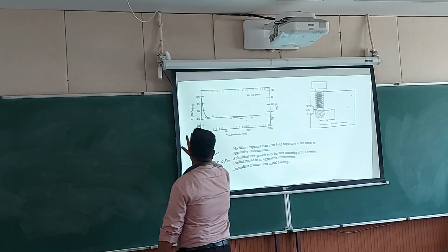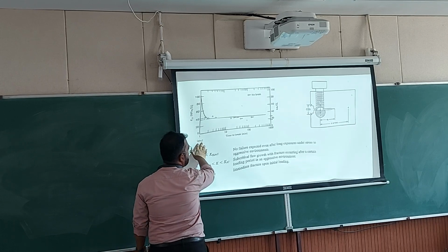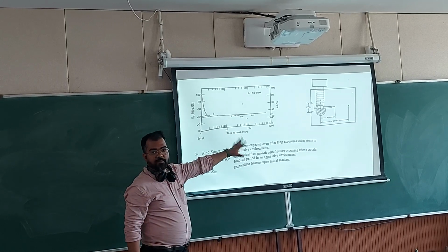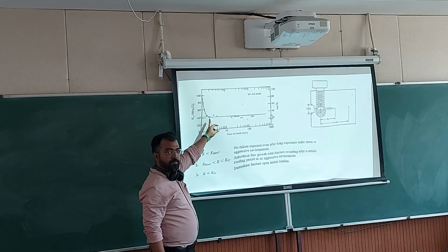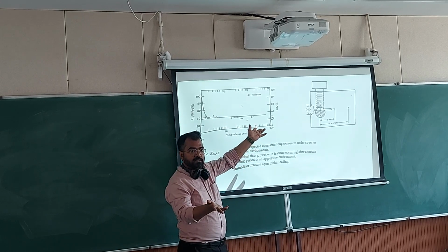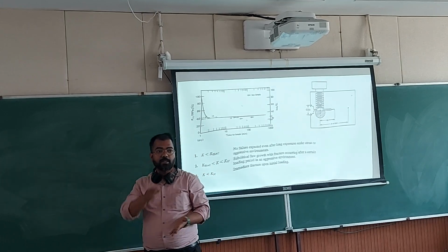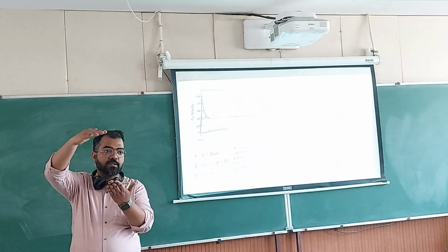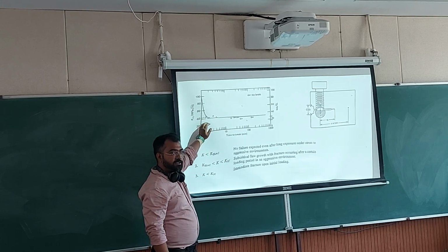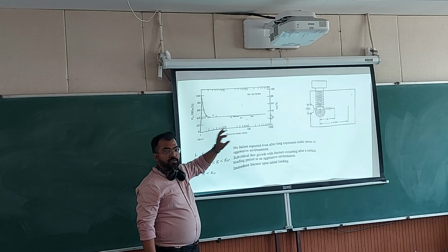And then when you do fracture testing, so you calculate K versus time, and this is dry, so there is no environment, no influence of environment, and then you put the environment and let the time do its thing, and then what happens? K drops, okay, and these are the points which are showing no break, and above these points there are data points which show that it breaks into two pieces. So you do those experiments and then you draw a line at the boundary of no break and break situation, and you can get that above this line the material will break, below this line it's like endurance limit. Okay, so you have a stress below which fatigue failure will not happen. In this case you have a K below which if you put that environment for a very long period of time, even then there will be no influence.